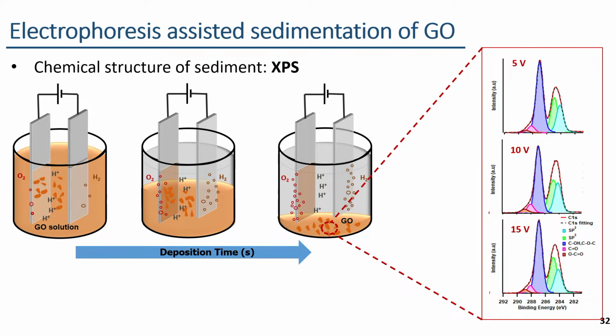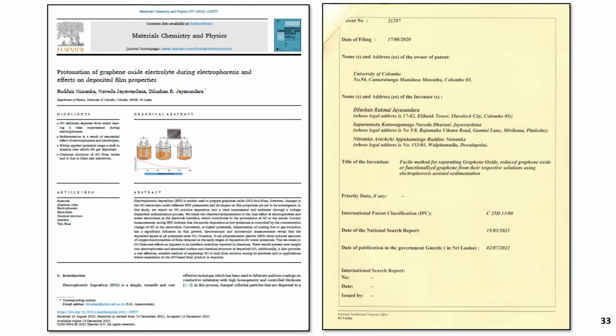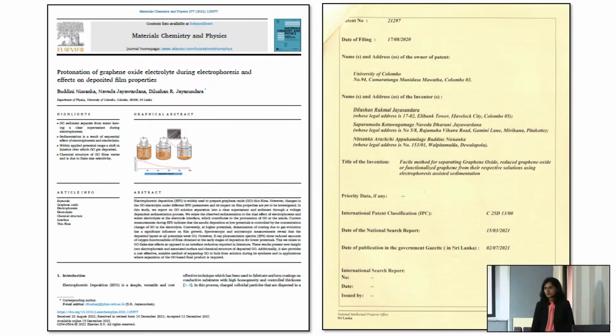At the same time, by properly applying these EPD parameters, this GO sedimentation method can be used to separate graphene oxide from bulk solutions during the synthesis of graphene oxide and its derivatives. At the end of this study, I was able to publish these findings in the Journal of Materials Chemistry and Physics. At the same time, this GO sedimentation method, which is used to separate graphene oxide from bulk solution, was patented in Sri Lanka.